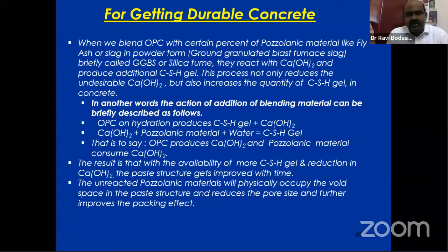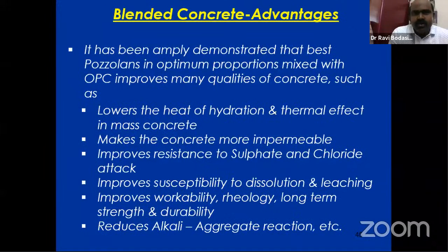As I discussed, in the OPC hydration process, CSH gel plus calcium hydroxide form, and the free calcium hydroxide, when again reacted with pozzolanic material and water, forms CSH gel again. So these pozzolanic materials will physically occupy the void space in the paste structure, reduce the pore size and further improve the packing effect. Once the packing effect is more and the void space is totally eliminated, you can get a dense and durable concrete. So these are all the advantages of blended concretes.